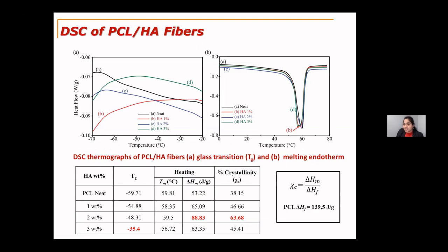After that, we checked the thermal stability of the fibers by doing DSC, differential scanning calorimetry, using a TA series instrument. Here I've shown the glass transition temperature for these fibers. For the polycaprolactone fiber, the glass transition temperature is around -60 degrees. That is very low. In general, PCL is particularly low compared to PLA.